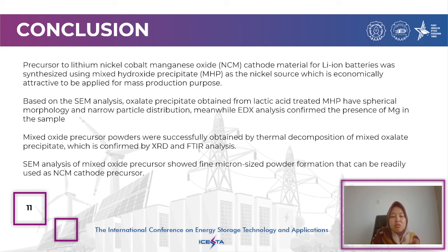Mixed oxide precursors were successfully obtained by thermal decomposition of mixed oxalate precipitate, which is confirmed by XRD and FTIR analysis. SEM analysis of the mixed oxide precursor shows fine micron-size powder formation that can be readily used as NCM cathode precursor.